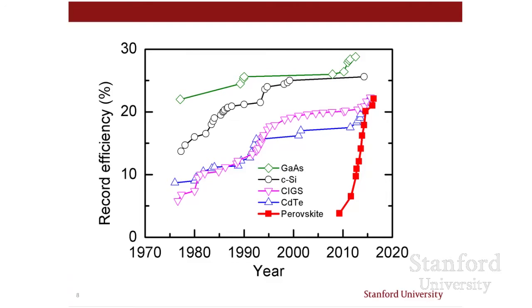If you look at the pink and blue, those are so-called thin film technologies, copper, indium, gallium selenide, and cadmium telluride. And the idea there is to use a smaller amount of semiconductor to try to reduce cost. And you can see the efficiency evolved over time, and now both of them are at 22%. But the news of today is that red curve, the perovskite. It just came out of nowhere around 2012, and the efficiency has soared up to 22, catching up with CIGS and cadmium telluride. And never in history has a semiconductor advanced so quickly for solar cell applications.